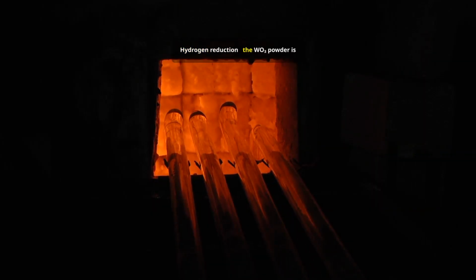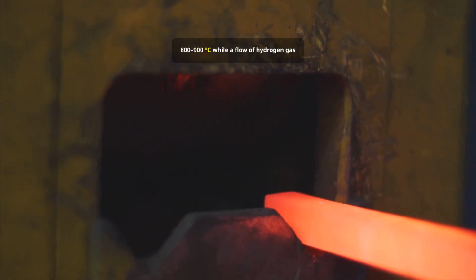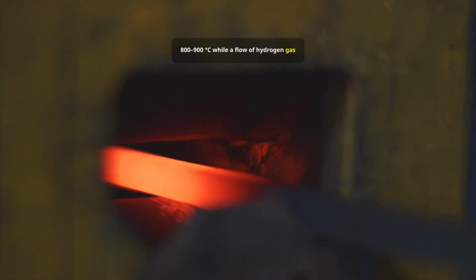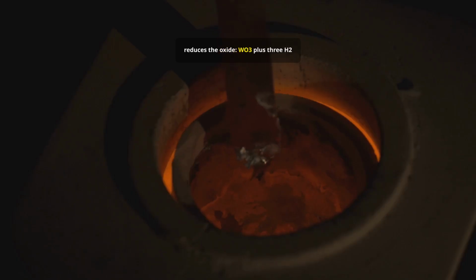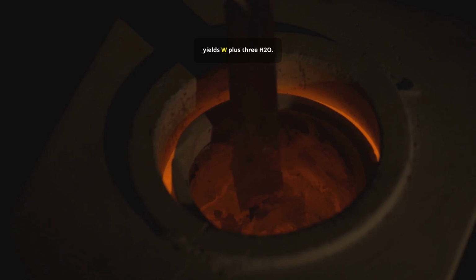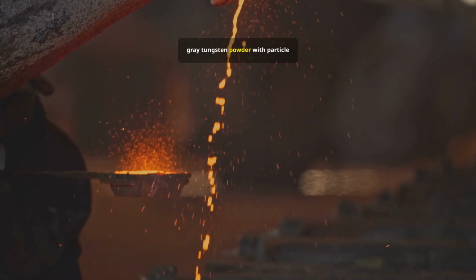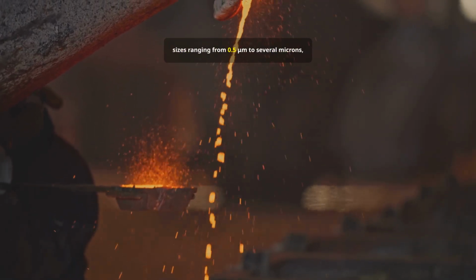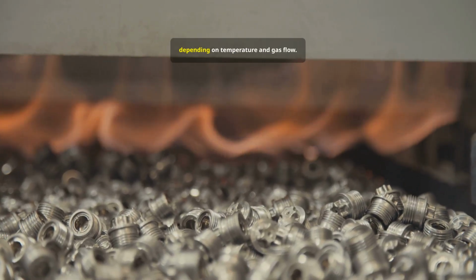Hydrogen reduction. The WO3 powder is placed in a tube furnace and heated to 800-900 degrees C, while a flow of hydrogen gas reduces the oxide. WO3 plus 3H2 yields W plus 3H2O. This yields a fine gray tungsten powder with particle sizes ranging from 0.5 μm to several microns, depending on temperature